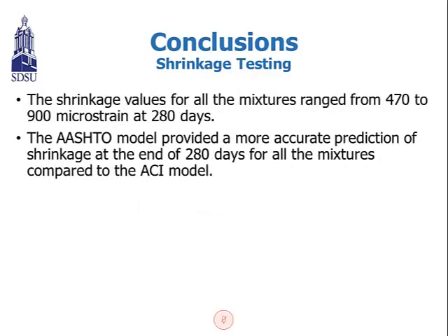And here's the conclusion for shrinkage testing. Shrinkage values for all the mixtures ranged from 470 to 900 microstrain at 280 days, and the AASHTO model provided more accurate predicted shrinkage at the end of 280 days for all the mixtures compared to the ACI model.